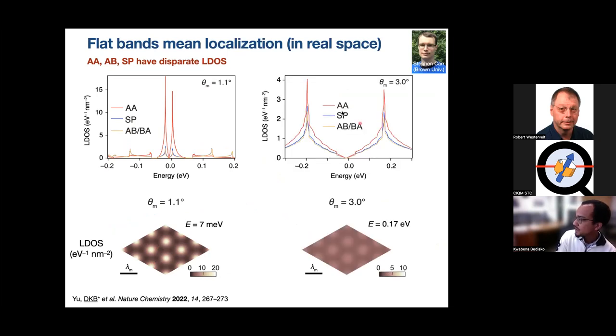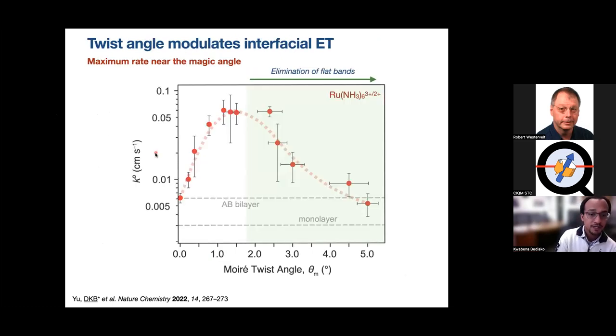That's what you see. And then if you go to about 3 degrees, then there is less discrimination between one stacking orientation and another. And this is just as you expect. So nothing too surprising there. So what we're learning, first of all, we can explain why there's this drop-off at large angles as simply because we're eliminating the flat bands as we go to larger angles. There's nothing too surprising there. But there is a question of what is happening at these smaller angles.